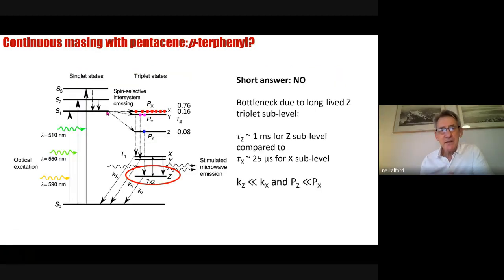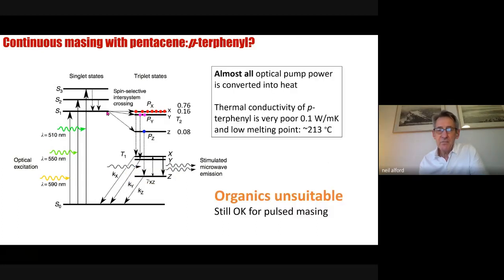So, can we make a maser work continuously with pentacene:p-terphenyl? And the answer is no, because there's a bottleneck. The spin dynamics do not allow us to do this in any case. Also, almost all of the optical pump power is converted to heat, and the thermal conductivity of the pentacene:p-terphenyl is very poor, we have a low melting point, and the organic simply melts under the maser power. So organics are unsuitable at the moment. Still okay for pulse masing, but not for CW.